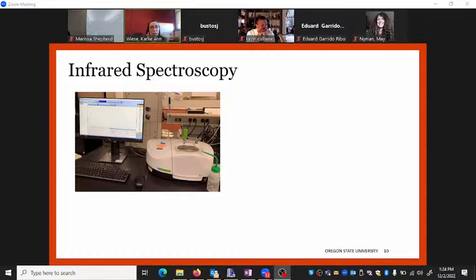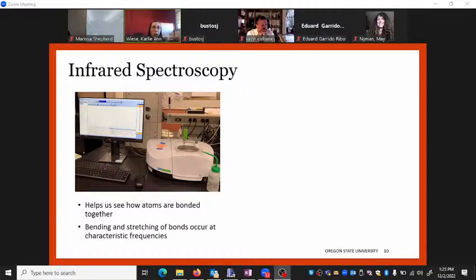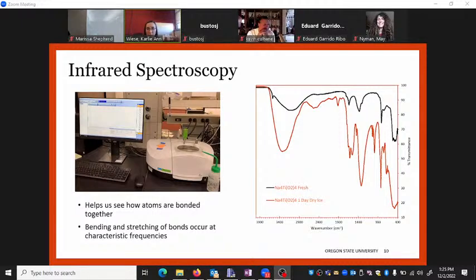This is a picture of the instrument that I use to do this. This helps us see how the atoms are bonded together. There's the bending and stretching of these bonds that occur between atoms. They have characteristic frequencies depending on what's bonded to what. Here's an example of some of my sample. The black line on top was the fresh sample, the white, and then after 1 day over dry ice, you get the orange here.